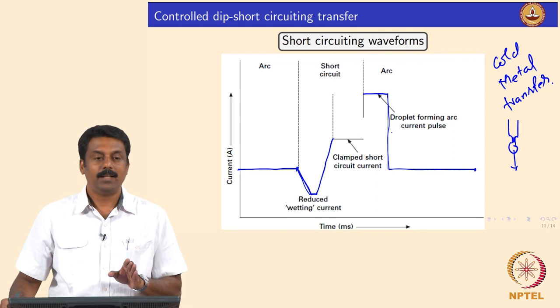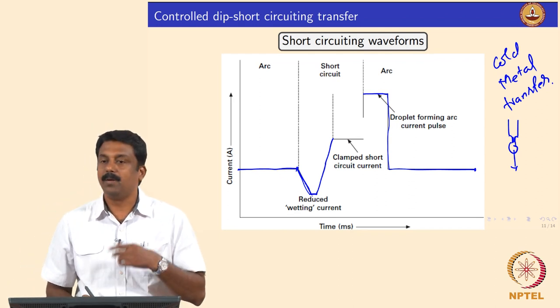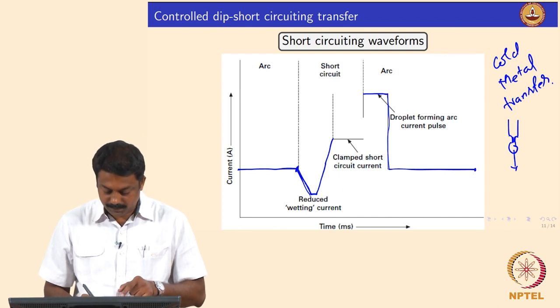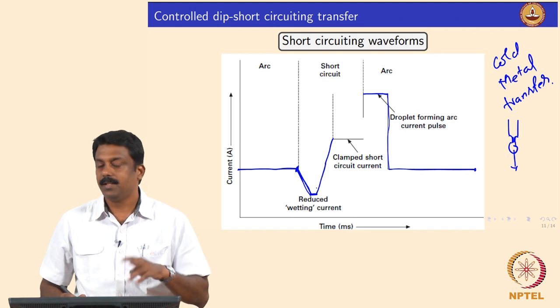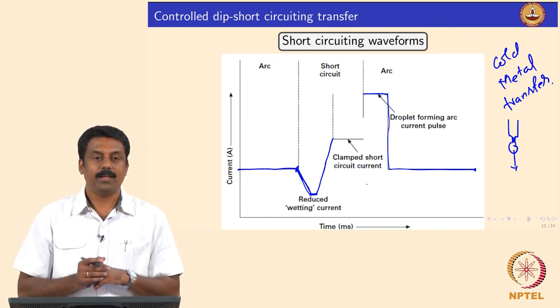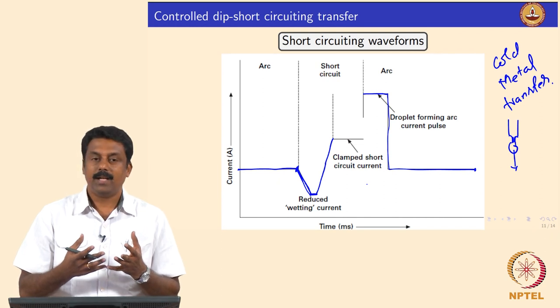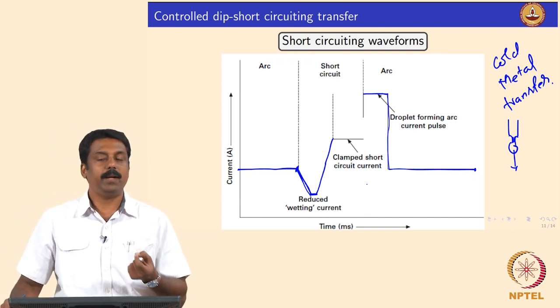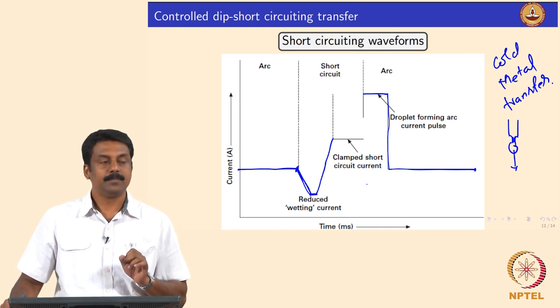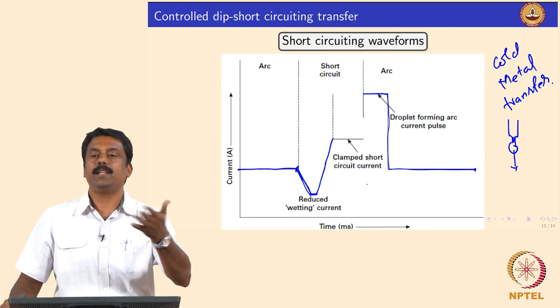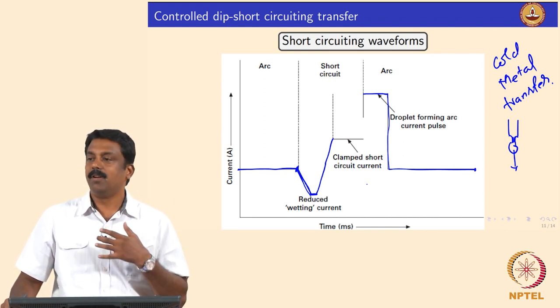The cycle then continues. The current is extremely low — even below arcing current — because the arc is completely gone. When the droplet is transferred, the voltage is zero and the current is very minimal because we are switching off the current when the short-circuiting happens. The droplet is therefore transferred as a technically molten droplet. The arc energy supplied is extremely minimized to a much lower level than even in pulsed GMAW. Technically the droplet is transferred at the melting point, meaning the droplet is transferred in a much colder stage than in any other GMAW process — that is why this process is known as cold metal transfer.